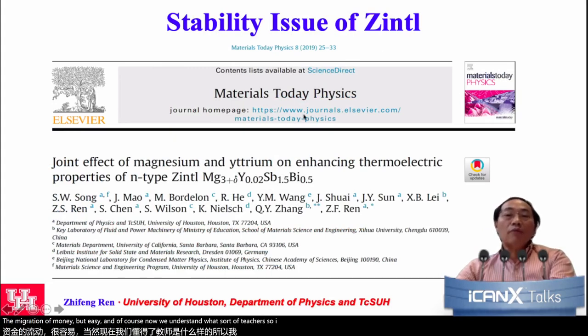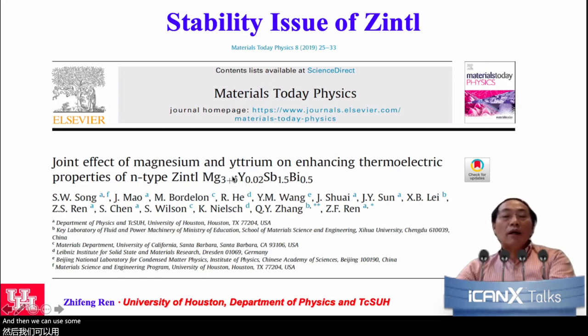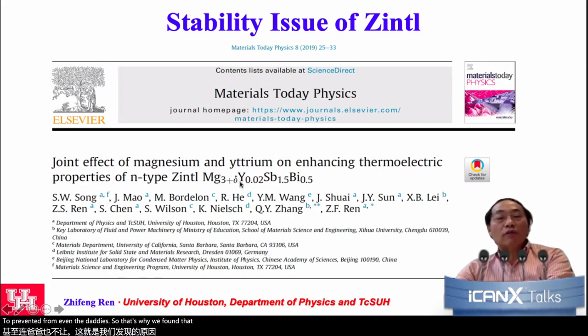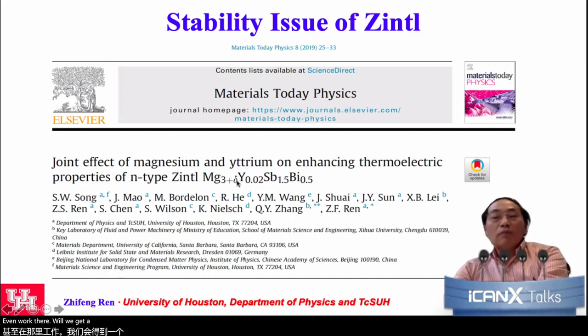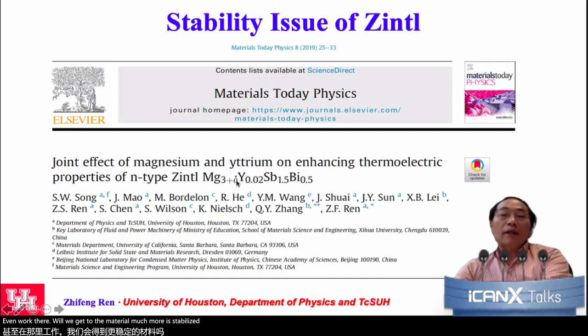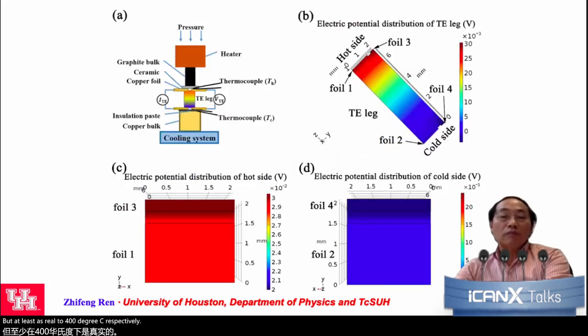So at that time we were thinking maybe we could use much less magnesium and then use some other elements as a pinning center, sort of, to pin the defects or pin the magnesium to prevent it from leaving the lattice. That's why we found that yttrium worked very well. We got the material much more stabilized, at least in the 300 to 400 degrees C range.